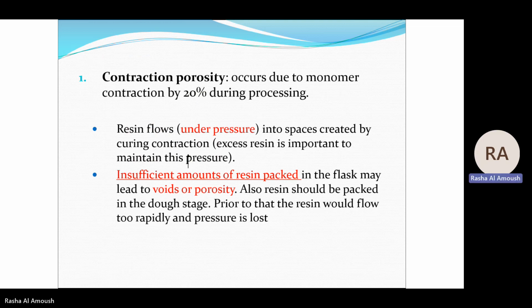Contraction porosity, as we said, happens due to the monomer contraction by 20% during processing. So the resin flows under pressure into spaces created by curing contraction. The excess resin is important to maintain this pressure. Insufficient amounts of resin packed in the flask may lead to voids or porosity. This is called underpacking. So if you have insufficient amount of the resin dough, this can lead to voids or porosities.